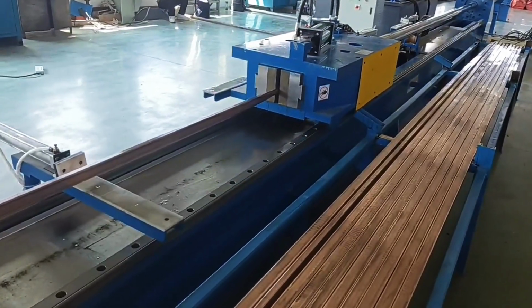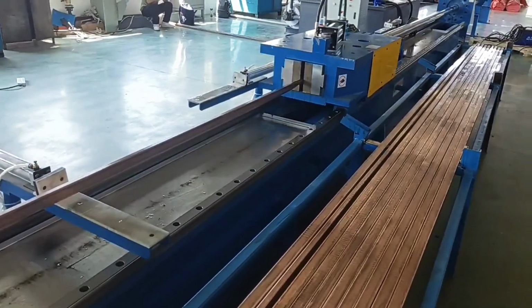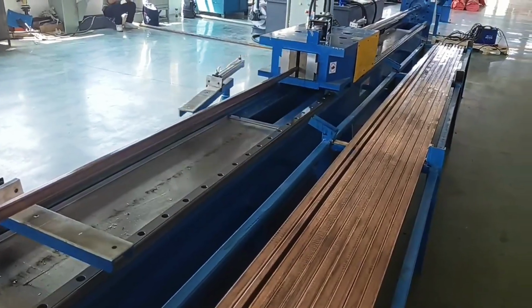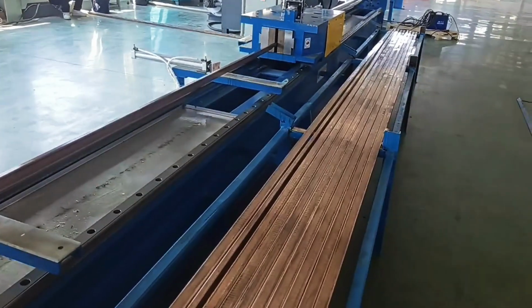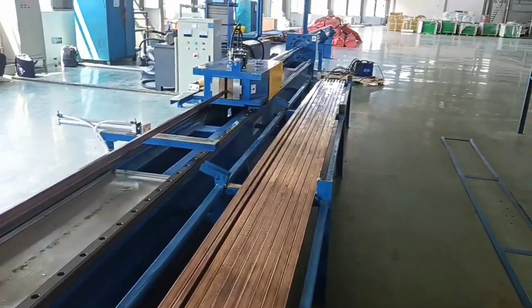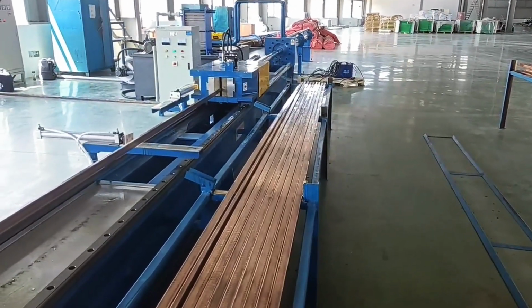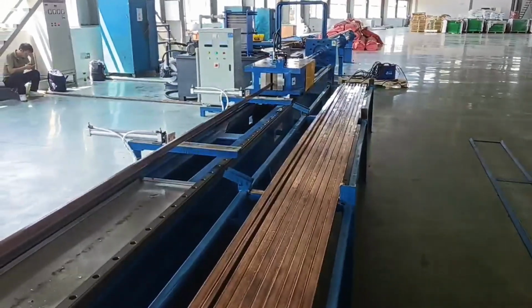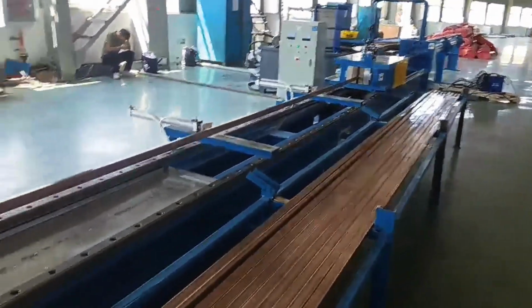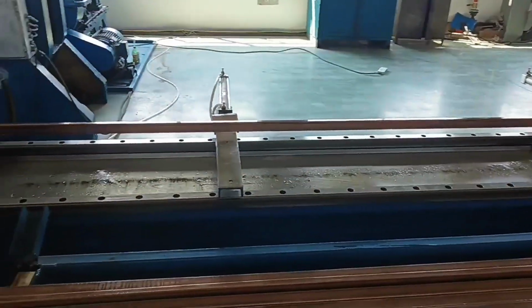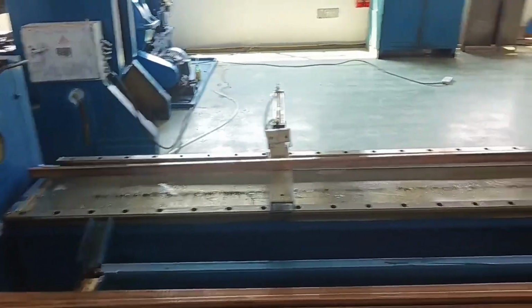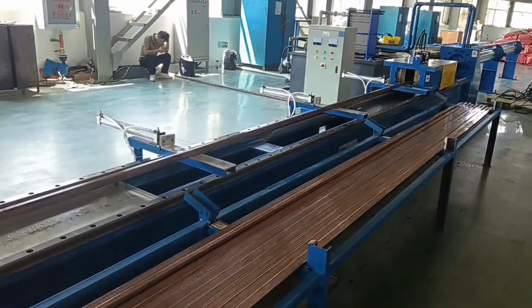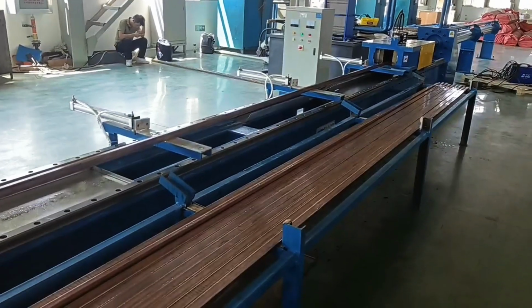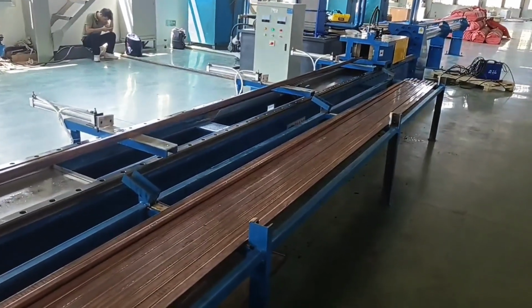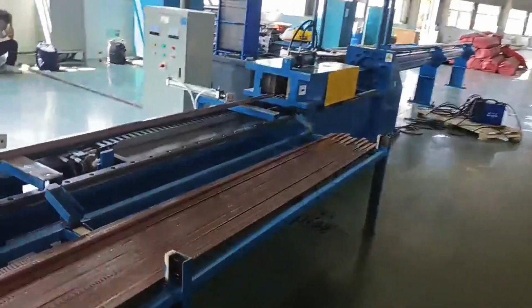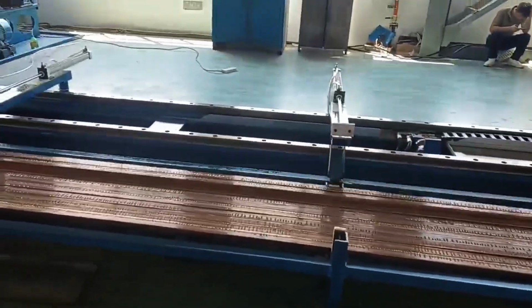Step 4. Insert the pointed end through the die from the backside. Step 5. The carriage grippers close onto the protruding point. Step 6. Activate the hydraulic system. The cylinder pulls the carriage at a steady speed, for a 10-ton machine, typically 5 to 15 meters per minute. Step 7. When the full length passes the die, the gripper opens and the drawn tube is unloaded. The whole cycle for a 3-meter tube may take just 30 to 40 seconds.